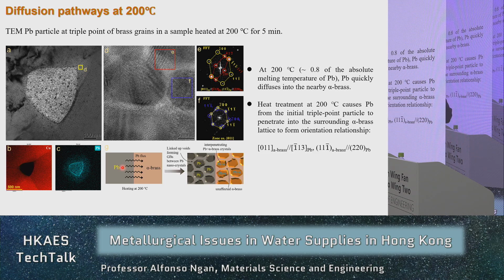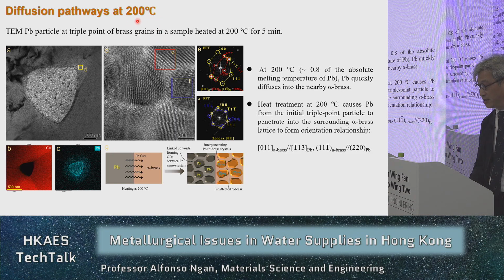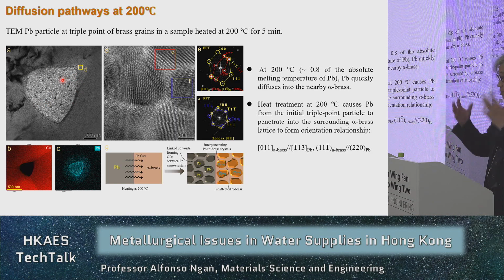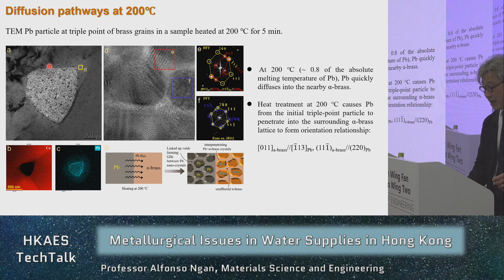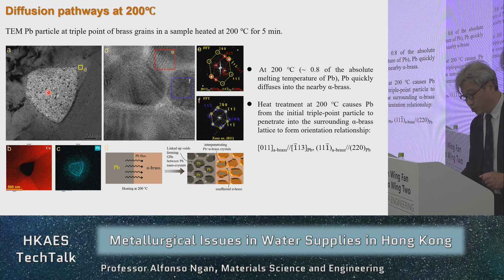So the spaces that become depleted of lead become the voids and look like the cracks. Okay, so that is, in a simple sentence, at 200 degrees Celsius, the original lead content will just diffuse away, forming this sort of maze-like structure.